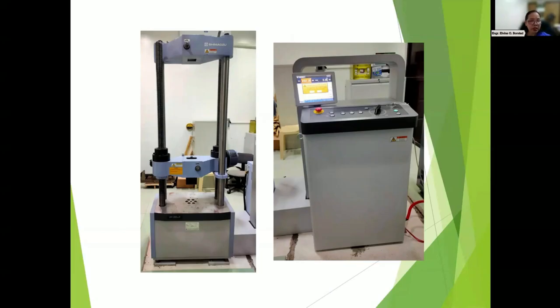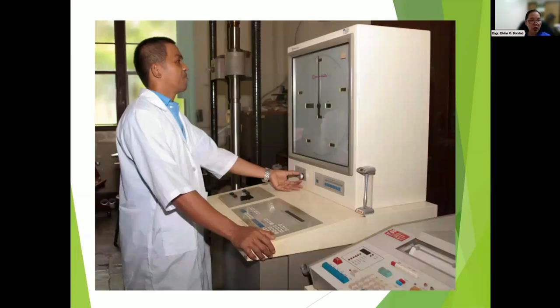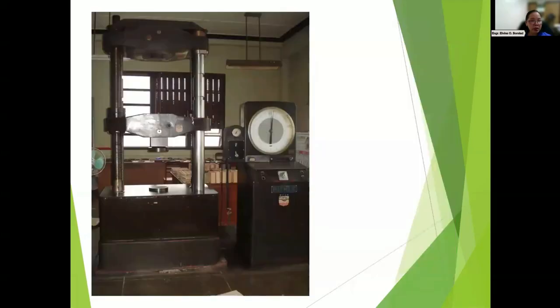We set the data, then we can easily get the mechanical properties, the modulus of elasticity, modulus of rupture, from the software. It's also our old UTM with a load capacity of 100 tons. It is the most old UTM for bigger capacity specimens like panel board, beams, concrete materials, pallets. Also in the testing of cylinder and hollow blocks. It is a 200,000 pounds load capacity, which is equal to 100 tons.